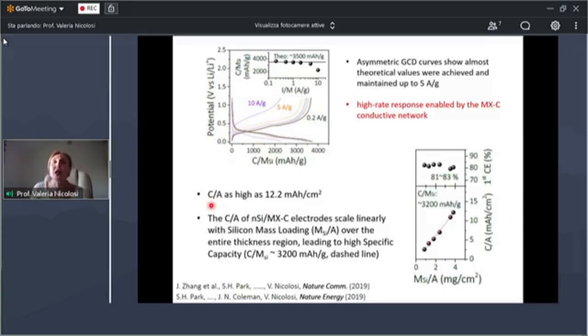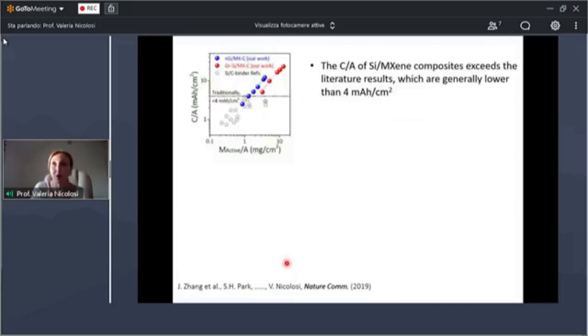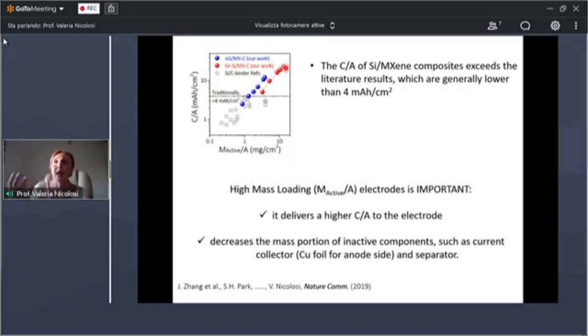By doing that, we could achieve a record areal capacitance of about 12 milliamps per hour per centimeter square, and theoretical capacitance of about 3,200 milliamps hour per gram. Very nicely, if you look at the areal capacitance as a function of the mass loading of MXenes here, the dotted line is what traditional standard commercial batteries can perform, about 4 milliamps hour per centimeter square. In blue and red instead, you see the performance of these devices. So we managed to hit a record performance only by adding about 30% of MXenes. So we were capable of delivering high areal capacitance at very, very minimal mass loading.